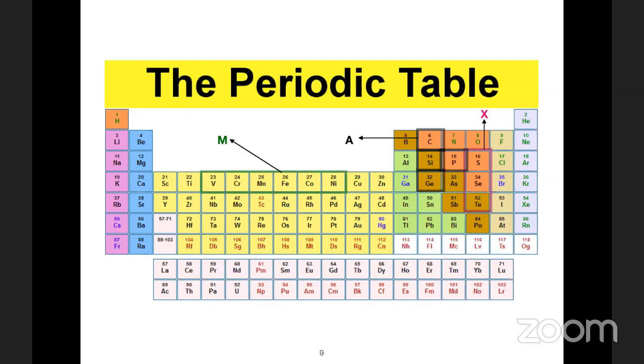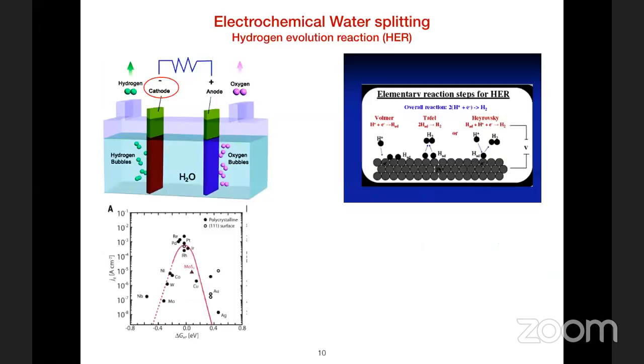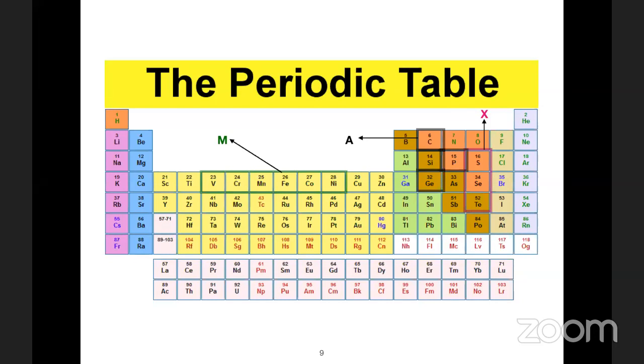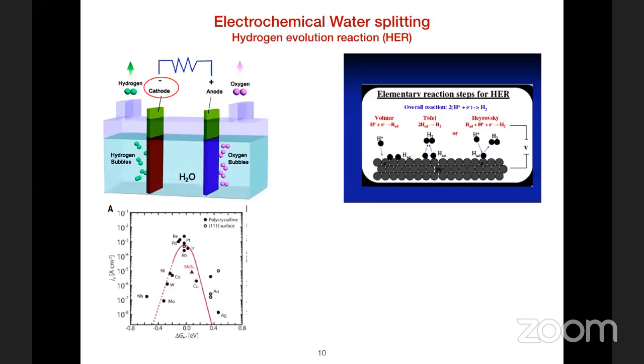But when you think about it combinatorially, there are many other possibilities. So are those compounds stable? Can they be synthesized? So what we did is that we took these 6 transition metal atoms, these chalcogens, and carbon, silicon, germanium and phosphorus as the middle atom to construct all possible compounds. And if you count the numbers, you will find that there are 72 compounds that are possible. And we basically studied all of them for their efficiency in hydrogen evolution reaction.